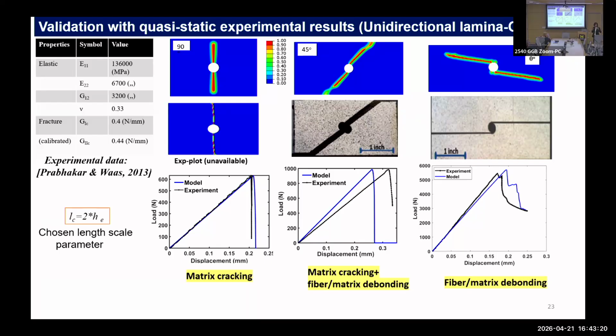So either of them you can choose. You can let the fracture parameter come from the experiments, and you can do a calibration on the LC. But then you have to control the mesh dependency there, because LC is used to resolve your crack surfaces, right? So it will depend on the mesh size. So here what we did is we fixed the LC depending on the mesh size. If we have a fine enough mesh, then we can fix the LC and then we calibrate the two toughnesses. That's all. And once we have that, you can see our models are fairly accurate at predicting the experimental response across the fiber orientation, and our predicted crack path matches the experiments fairly nicely.